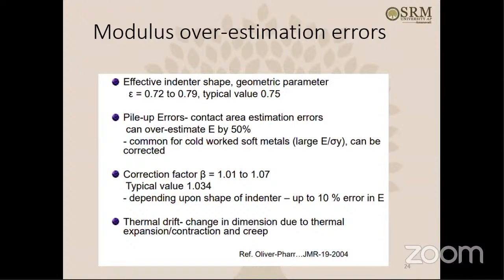So these errors have to be estimated properly, and then we have to come up with an approach to adjust for those errors. Okay. So sometimes it can overshoot. Models can overshoot by 50% because of pile up errors. Okay, it's common for cold worked soft metals with large E over sigma Y. It can be corrected. Okay. Then correction factor beta, that also varies in a range, so it can be adjusted, and then corrections can be done depending upon the shape of the indenter, up to 10% of error in modulus.